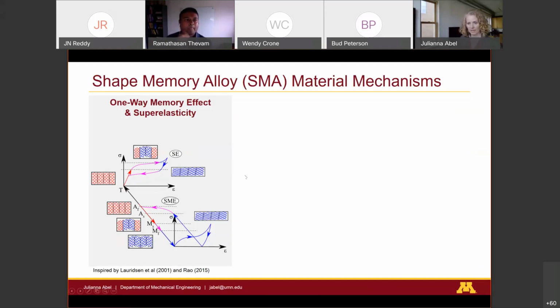Another common effect that's been used frequently is the shape memory effect. That's when you're actually changing the temperature. So instead of just dealing in stress-strain space, now you're dealing with stress, strain, and temperature. You're going from a cold, flexible, martensitic state, and then as you heat it up, you recover those deformations in the wire, and you can do mechanical work during this process.